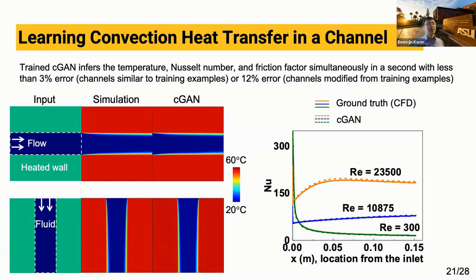And then we also tested the model using somewhat modified channel geometry. So for example, here we supplied a 90-degree rotated channel, but still the generator network was able to predict temperature distribution, something like this.